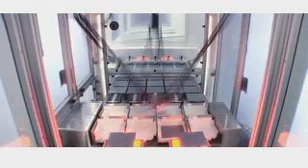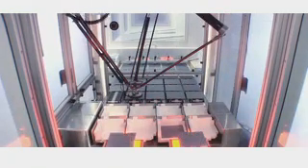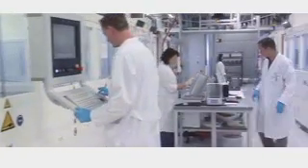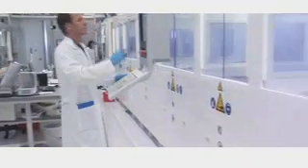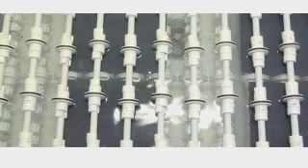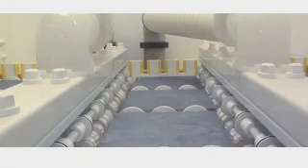Here, any residual chipping is removed from the raw wafers in a wet chemical process. The wafers are then cleaned prior to further processing. They undergo automatic etching, followed immediately by rinsing in different basins. The raw surface of the wafer is removed in the etching bath, which contains caustic potash solution. Following this, the wafers are dried.